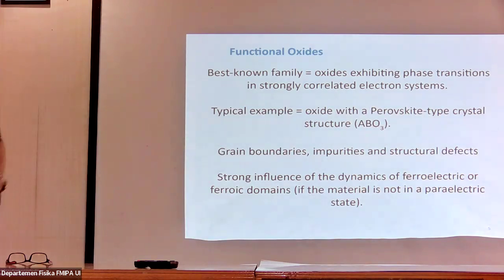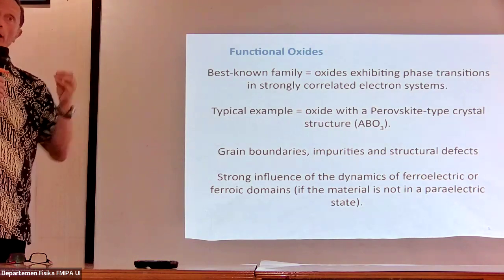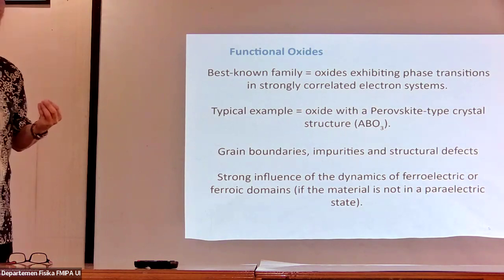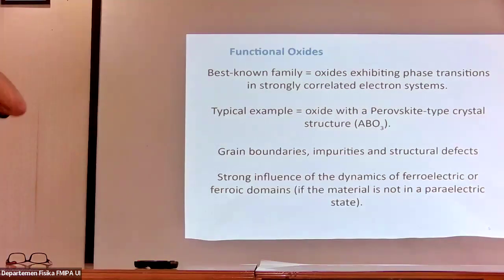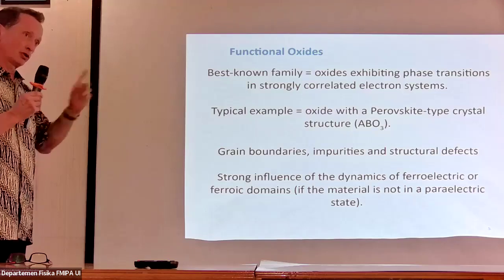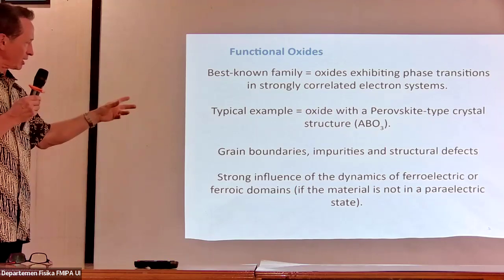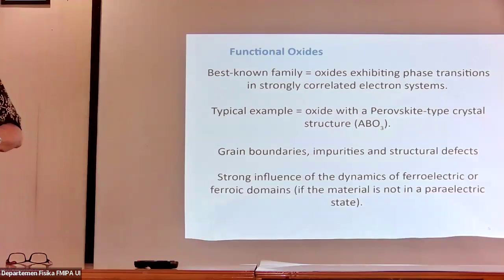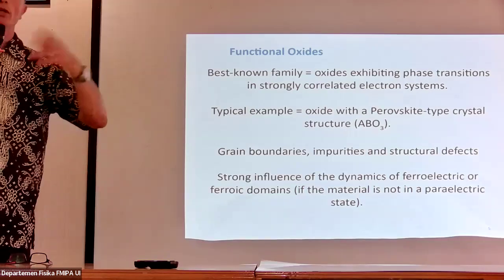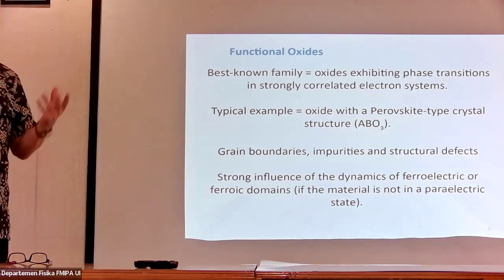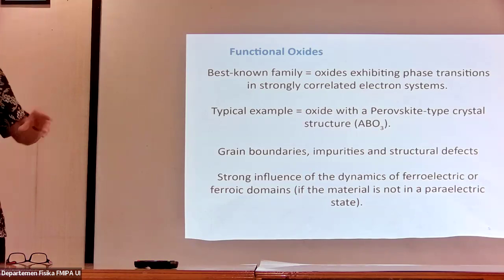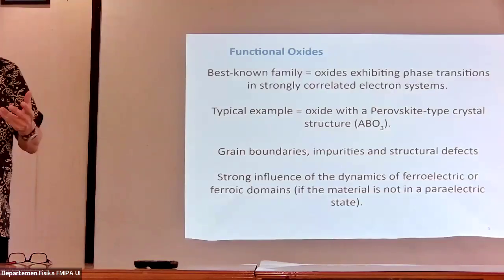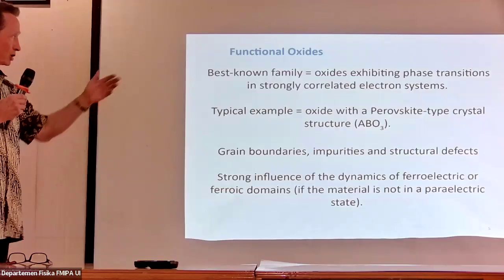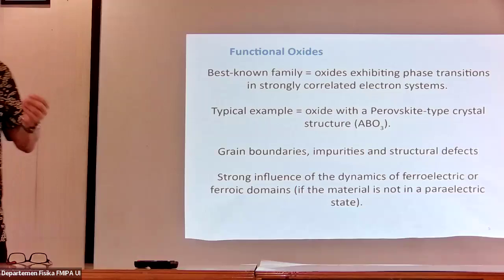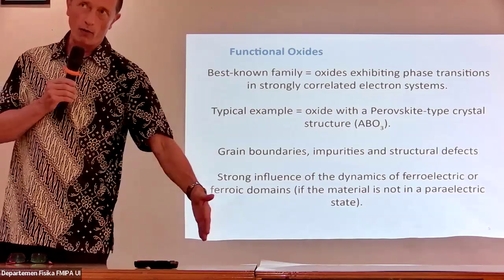In an oxide, effectively, you also have a special structure, because we have grains. And if we talk about grains, between each grain, we have boundaries. So these boundaries are a special area in the material where you have crystalline discontinuities, and you have different, modified properties, due to this inherent structure. It's not possible to fabricate a perfect material. So every kind of material includes impurities, and these impurities will have a huge effect on the properties. Structural defects. Structural means in the crystalline structure; when we develop a material, we are far from the theoretical structure.